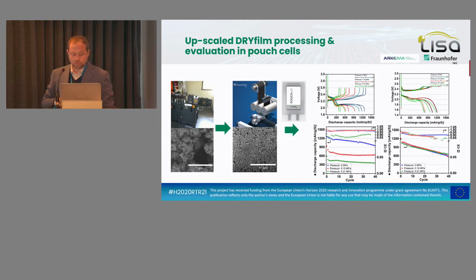This is another process for cathode manufacturing. Here Arkema makes a material by co-extrusion of carbon nanotube and sulfur. And after, you have the process from Fraunhofer that is dry processing, meaning without solvent. So you have this 3-roll mixer now, and basically you can lift up the cathode from your current collector. So, dry manufacturing.